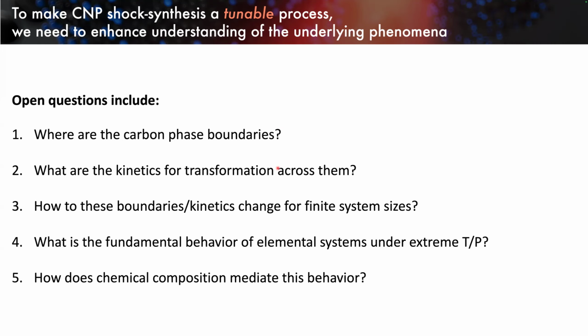The kinetics here matter because the solidification process I talked about is a non-equilibrium process, so we won't necessarily get what the equilibrium phase diagram would suggest for a given thermodynamic quenching pathway. We also need to understand the impact of surface free energy, since we're dealing with finite size systems. The result we get for a nanoparticle versus bulk carbon will be different.